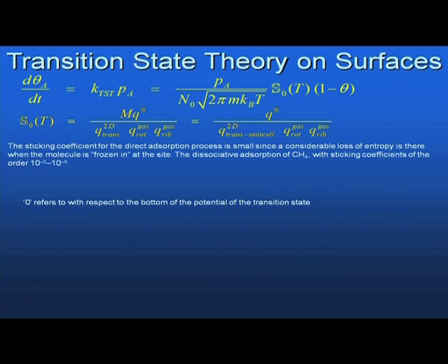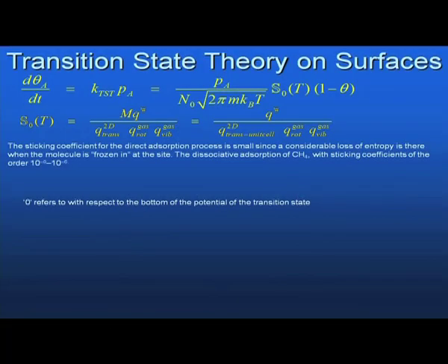Once it gets a site, it remains over there for time. So, it is frozen, it will not move anywhere, it has the option to just move along the reaction coordinate. Okay. An example is the dissociative adsorption of methane, which has a sticking coefficient of the order of 10 to the power minus 8 to 10 to the power minus 6. It is very small. Okay, it is a very small quantity.